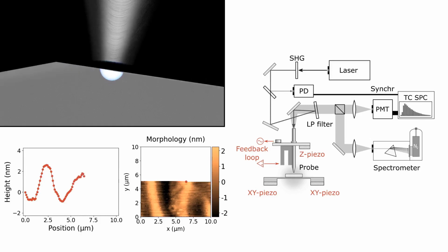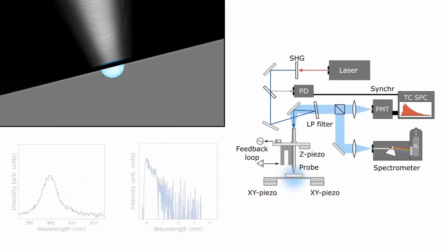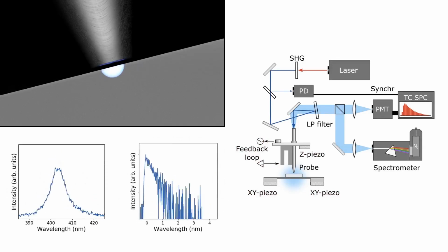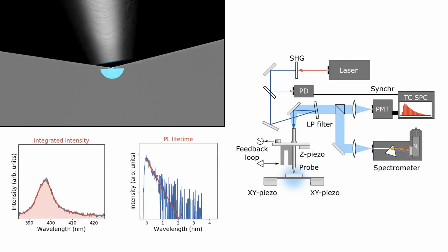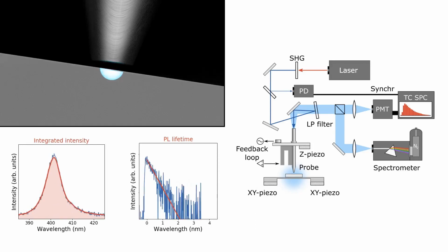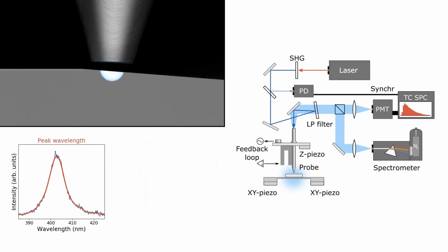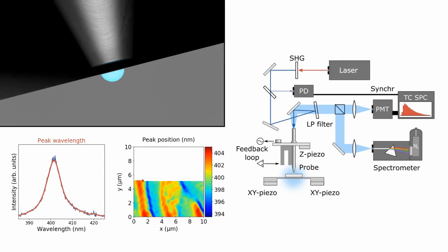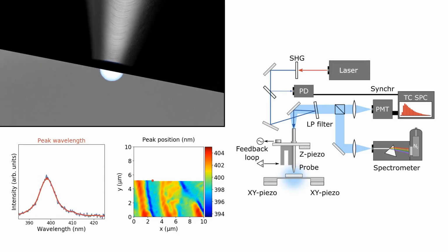The optical signal is then collected back through the probe aperture and analyzed outside using a time-correlated single photon counter and spectrometer, which then allows measuring different optical properties and, for example, taking photoluminescence peak wavelength spatially mapped.